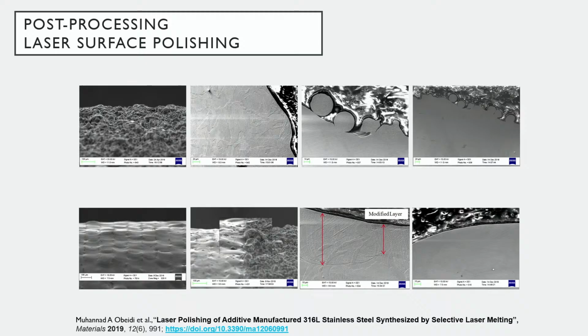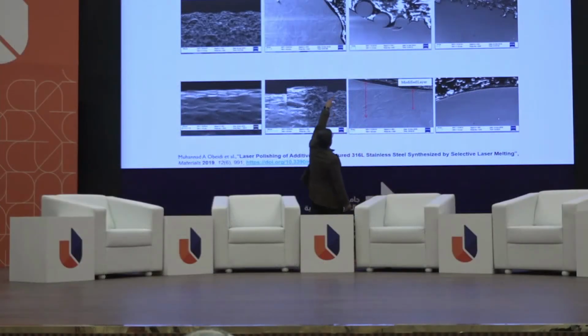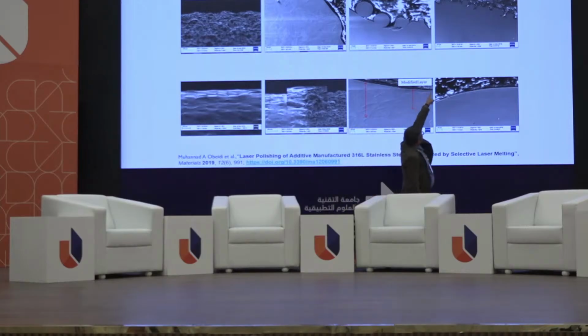Laser polishing, and we have very good experience with that. So you can compare the top surface after printing, before polishing. This is the modified and polished layer. You see these stair steps here, which is there and there. I melted the particles and relocated them from the top high peaks to the lower valleys. And then at the end, that is the cross-section of that cylinder that you saw. It came out like this after polishing on the same magnification scale.